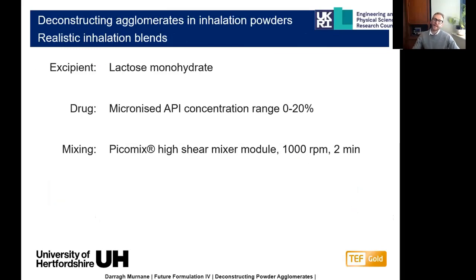So if we take then those agglomerates, how do we formulate those? Well, we'll typically take an excipient, this lactose monohydrate diluent. We'll take a micronized API, an active pharmaceutical ingredient, and that's in the concentration range of about 0 to 20%. And nowadays, it's most common to undertake a high shear mixing approach. So we took a variety of these blends and an experimental design. We're just going to show you one of these throughout the results.